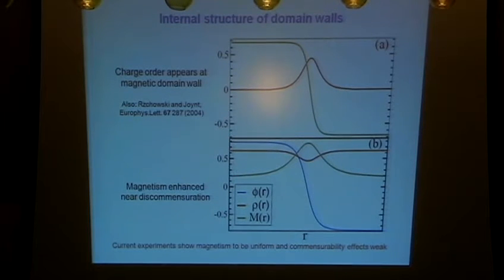Now, the other thing it does is it plays out very interesting structure with the order parameters playing off against each other. So, for example, at a discommensuration, if I was in this charge ordered phase, so here's a discommensuration, this is the kink of the phase, it turns out that it suppresses the charge order parameter and enhances the magnetization.